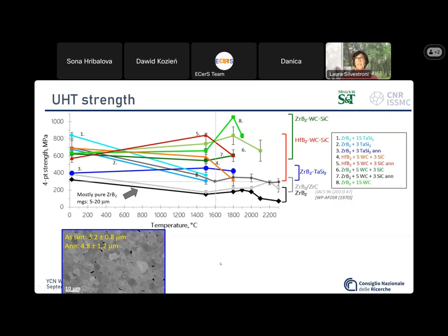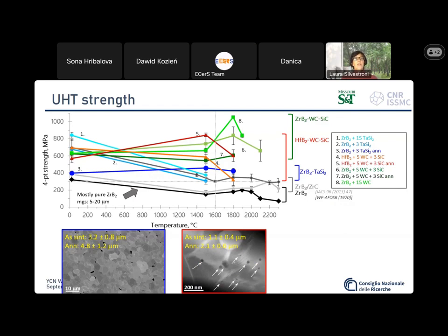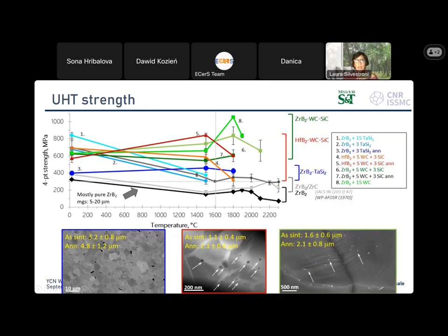We prepared another material, in blue, where the second phase was completely consumed during the thermal treatment, but still had a finer grain size, resulting in a constant strength, here in blue, around 400 megapascal from room temperature up to 1800 degrees C. Another interesting result was obtained for our hafnium diboride based system that you see in orange and red. The orange is the as-sintered and the red one is the annealed. We measured a strength increase of 300 after the annealing due to the development of the shell with the tungsten inclusion.